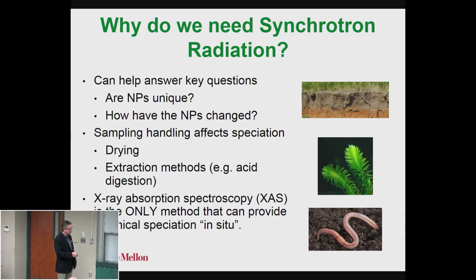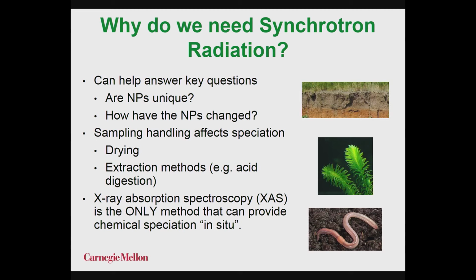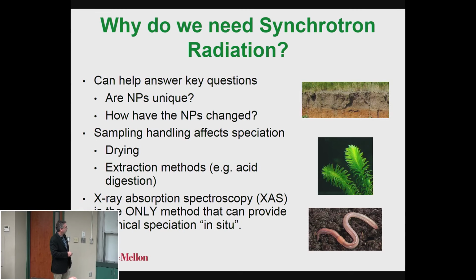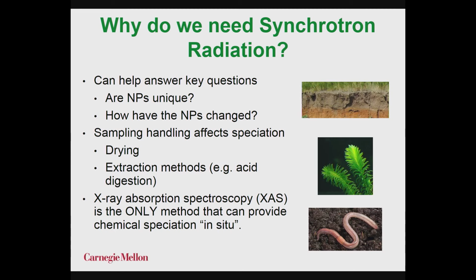So we can do this in situ. I can actually take a worm and put it into a beam. I usually dry it or lyophilize it and crush it up first, but you'll see some of the things we do with X-ray fluorescence, we can just put the worm right in, right? So X-ray absorption spectroscopy is the only method that can give you in situ metal speciation of these materials. And this is really why we use it.